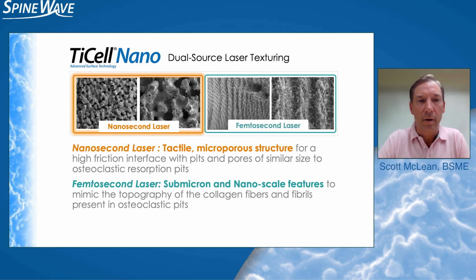So first, we are using the nanosecond laser to create a tactile microporous structure. And that provides a high friction interface between the end plate of the implant and the vertebral end plate. And you'll notice that there's pits and pores on this surface that are of a similar size to osteoclastic resorption pits. Second, the femtosecond laser produces submicron and nanoscale features. And as Dr. Boyne mentioned, these are the features that mimic the topography at the base of the osteoclastic resorption pit, the collagen fibers and fibrils present in that area.